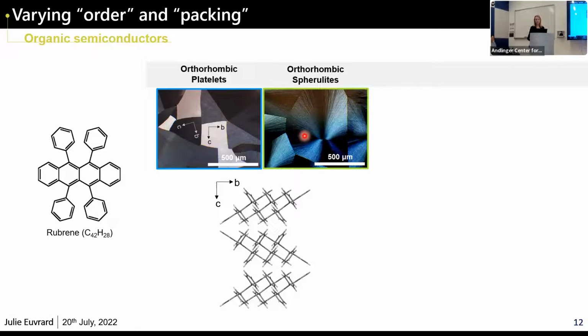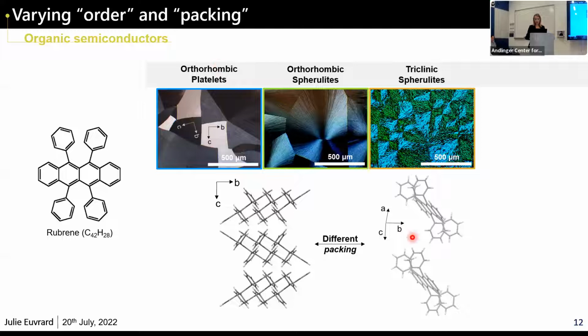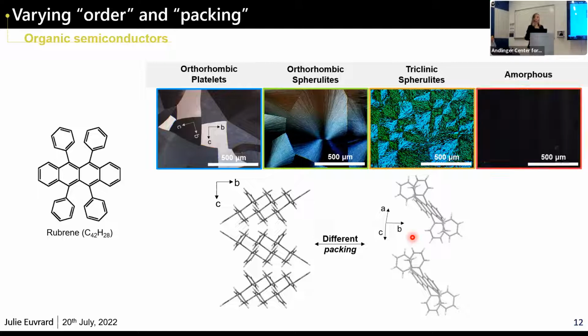So that's about order. What we can also change is packing. So here in those films, the molecules arrange in this particular packing, which is called orthorhombic. Now what you can do is change the packing, and the molecules can form a triclinic crystal phase, and we'll see how that impacts transport. And finally, you can have fully amorphous rubrene. So this offers a perfect playground to look at how order, but also packing, impact transport properties.